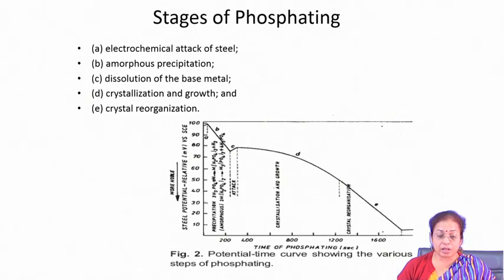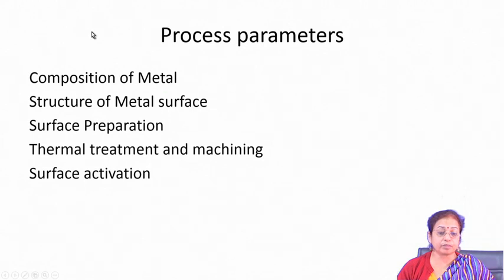If you see the surface carefully, you will find that the phosphates are flaky in nature, and between two or three flakes there are a lot of porosities. These porosities are very good when you do a painting operation on the phosphated layer, because there is seepage of the paint into the porous or interflake regions, which improves the adherence to the surface.